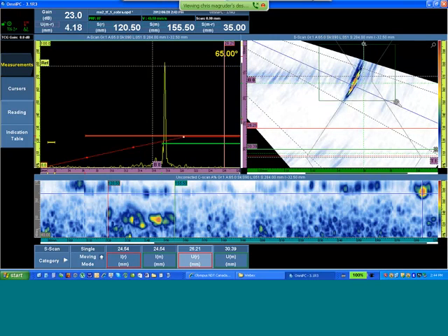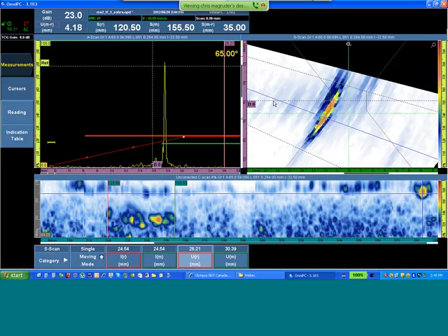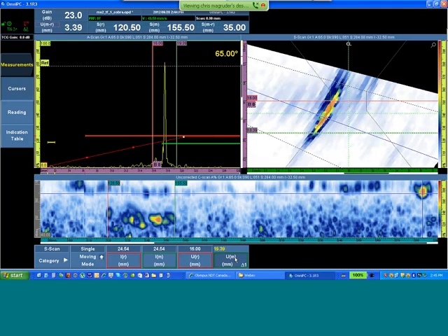To size that, we would assume one of our cursors is directly at B0, and that's at a depth of 16 millimeters. So I'll just type it in directly. I will use my better indication on the second leg to identify the top at about a 3 dB drop.